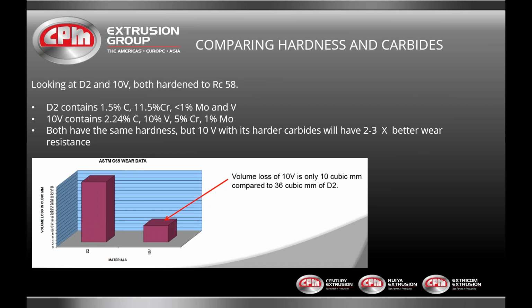Comparing the hardness in carbides, looking at D2 and 10V, both hardened to Rockwell C58. D2 contains 1.5% carbon, 11.5% chrome, and less than 1% molybdenum and vanadium.